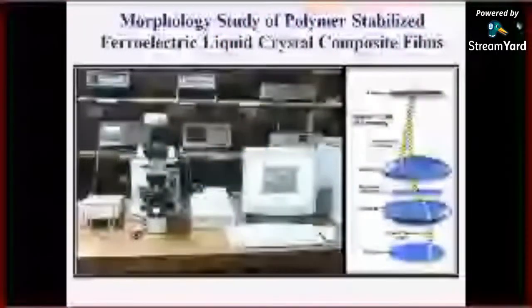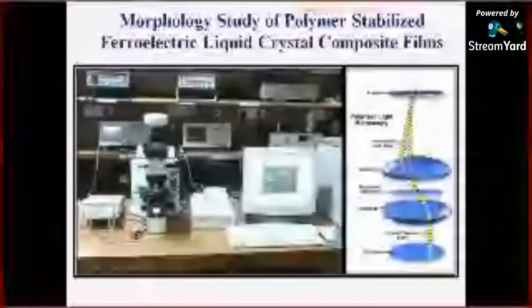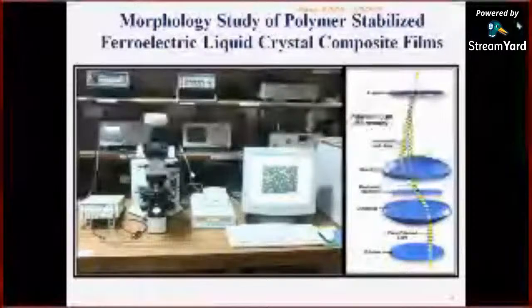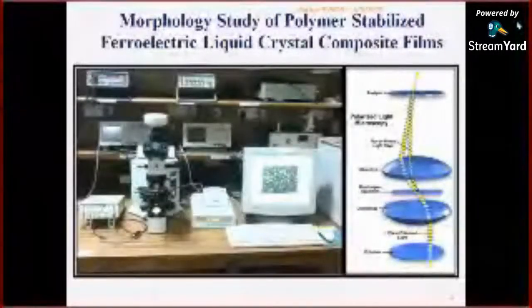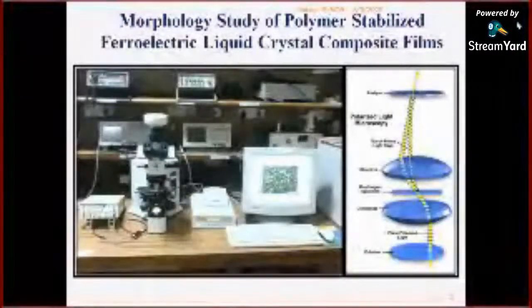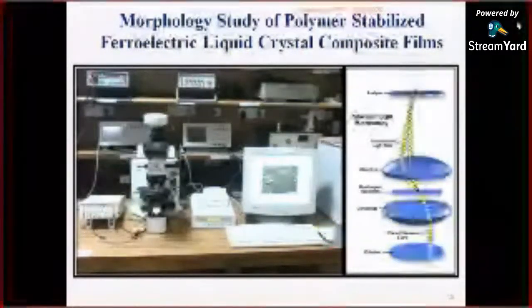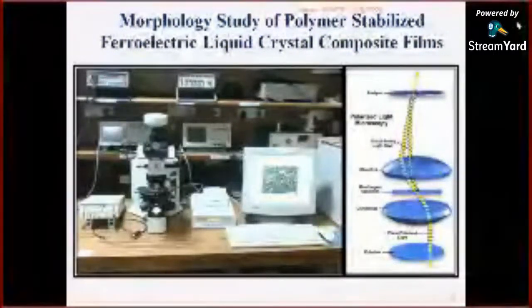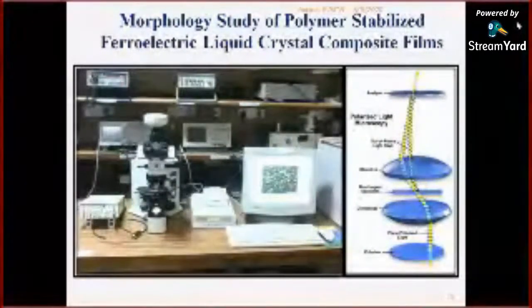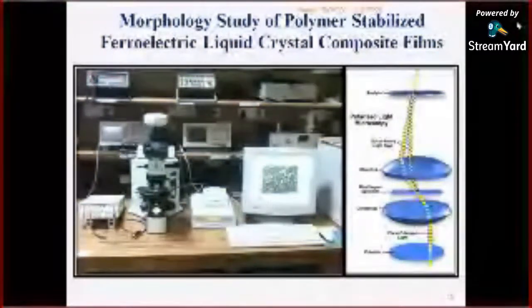So these are the setups in the labs where we have studied the electro-optic properties of this liquid crystal system. This is the polarizing optical microscope, and this is the hot stage to measure the response with temperature. That hot stage is connected with this temperature controller. We control the temperature from this device, and we put the sample here. So by using these apparatus, we can measure the response with respect to changing the temperature of the liquid crystal,